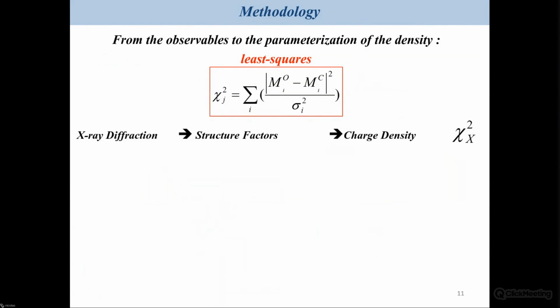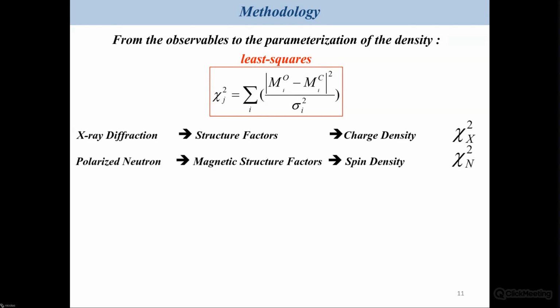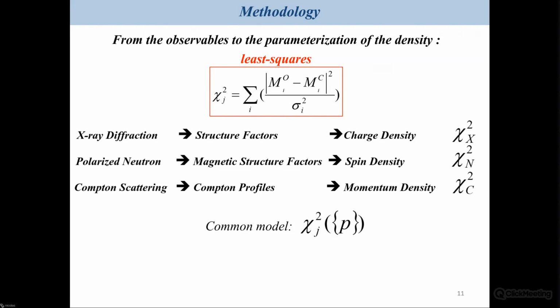If you consider any isolated experiment, for example X-ray diffraction, you will extract structure factors from the X-ray diffraction. That is the way to model a charge or electron density, and for that you define a chi-square. You will do exactly the same for polarized neutron diffraction. That gives you the magnetic structure factors, which help you model the spin density with another chi-square. And again, you can do that for many different experiments. But the question at the end is: what could be the common model for all the experiments? Moreover, what is the function to consider to refine that model, and what are the parameters I have to consider to refine it? So many interesting aspects that are not so easy to answer.